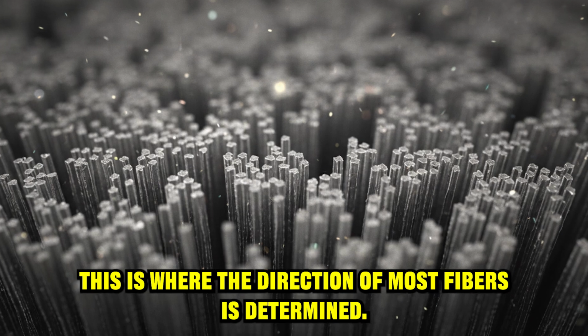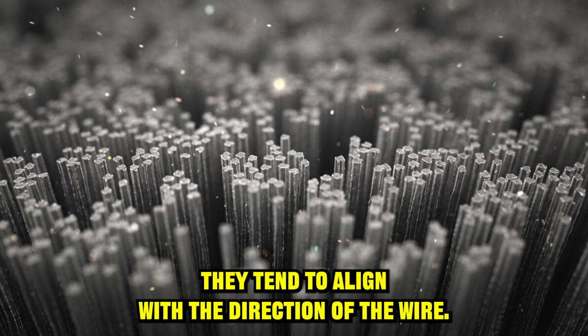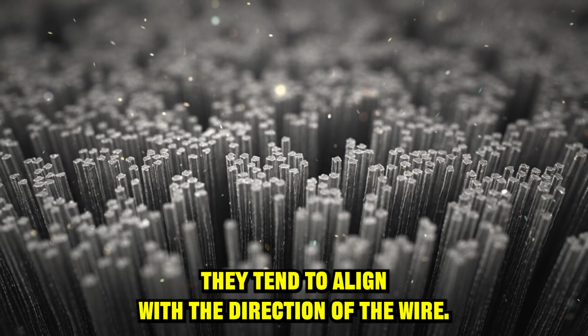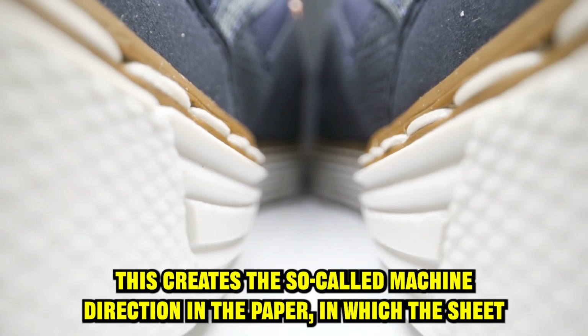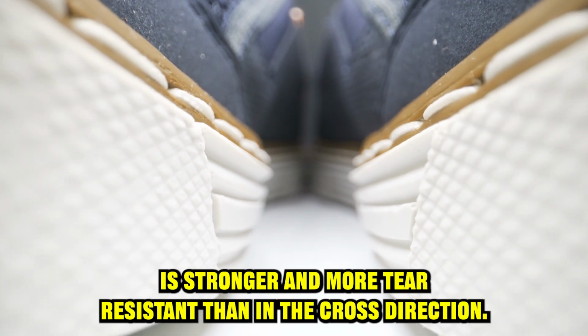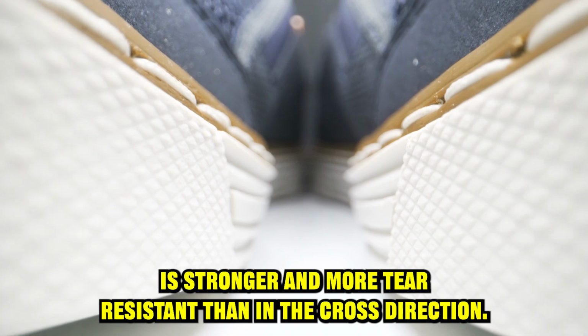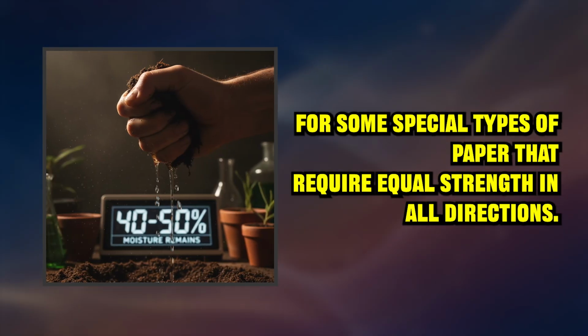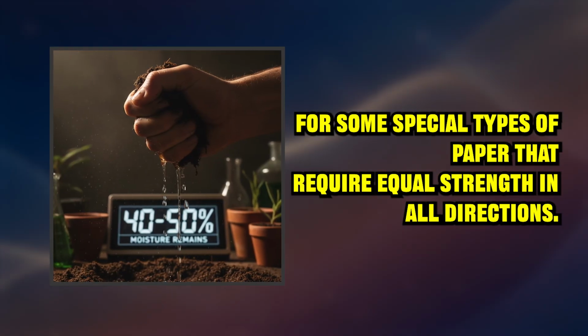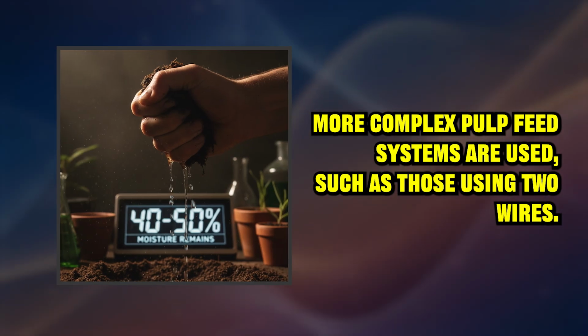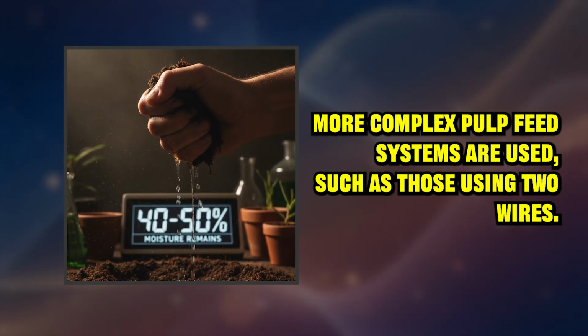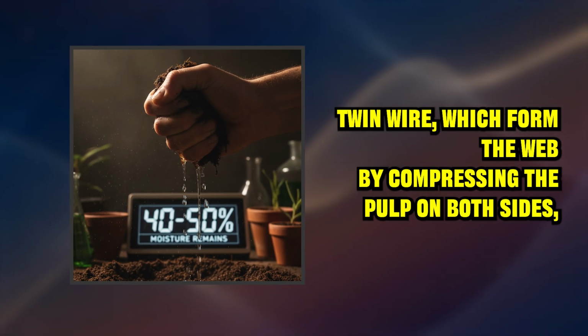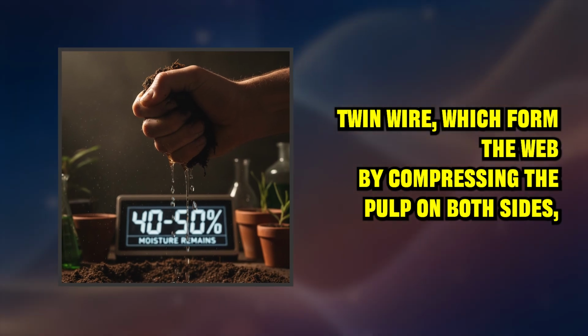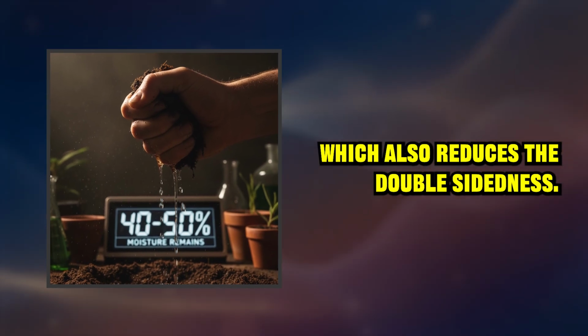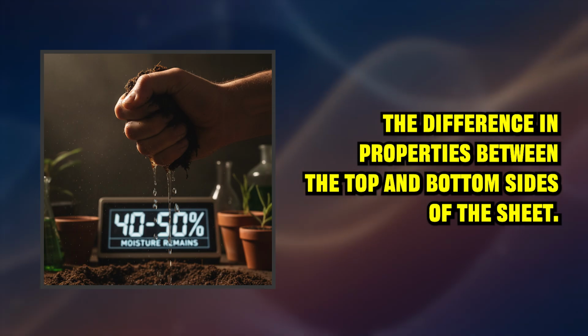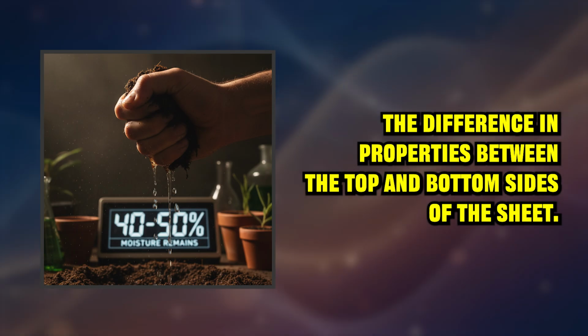This is where the direction of most fibers is determined. They tend to align with the direction of the wire. This creates the so-called machine direction in the paper, in which the sheet is stronger and more tear-resistant than in the cross direction. For some special types of paper that require equal strength in all directions, more complex pulp feed systems are used, such as those using two wires, twin wire, which form the web by compressing the pulp on both sides, which also reduces the double-sidedness, the difference in properties between the top and bottom sides of the sheet.